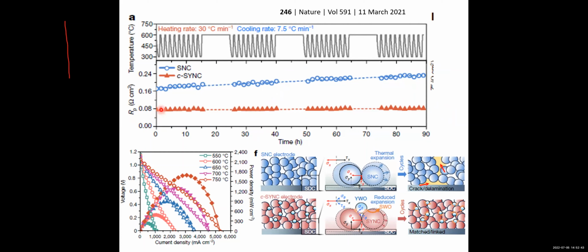Using this approach, we can successfully decrease RP, the polarization resistance. In long-term operation, especially after thermal cycling where we heat up and cool down the fuel cell for about 40 cycles, we find the fuel cell still works very stably.